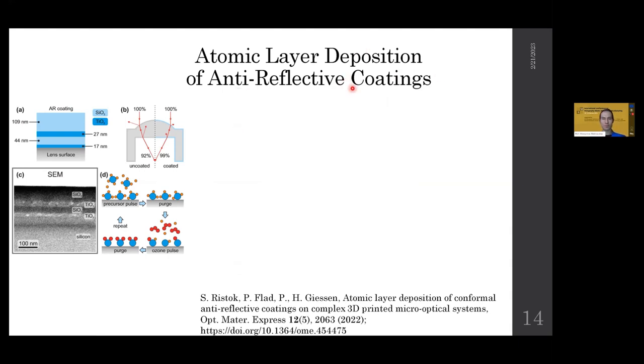exploiting atomic layer deposition. This image represents the principle, which was shown a year or slightly less ago by Professor Harald Giessen from Stuttgart University, where they coated an anti-reflective coating on their made micro lens. Actually I would call it a millilens because it was almost 5 millimeters in dimensions, but the applied principle of using atomic layer deposition allowed them to coat silicon dioxide and titanium dioxide coatings to make it transparent for visible wavelengths and increase the transparency factor from 92% to 99% with this multi-layer coating.